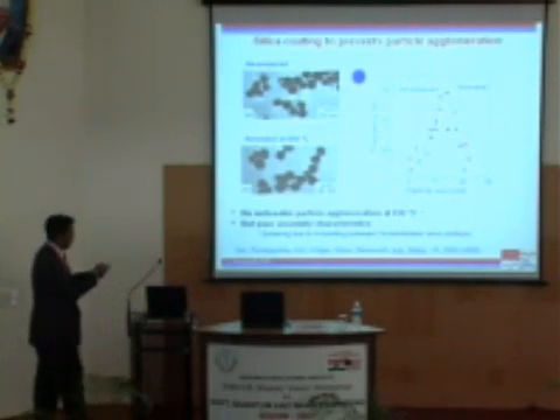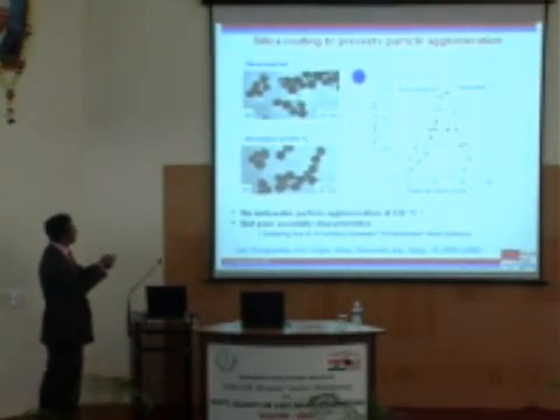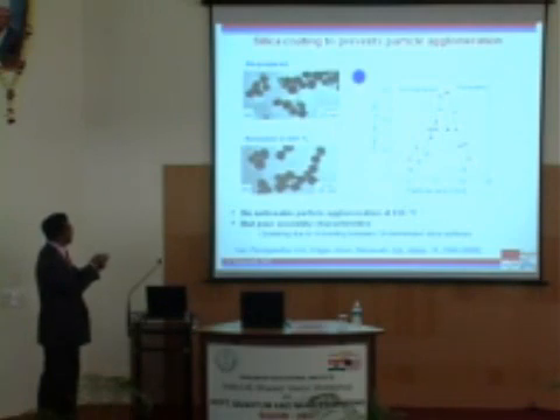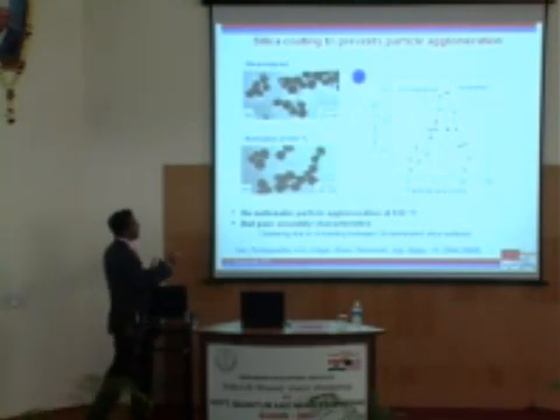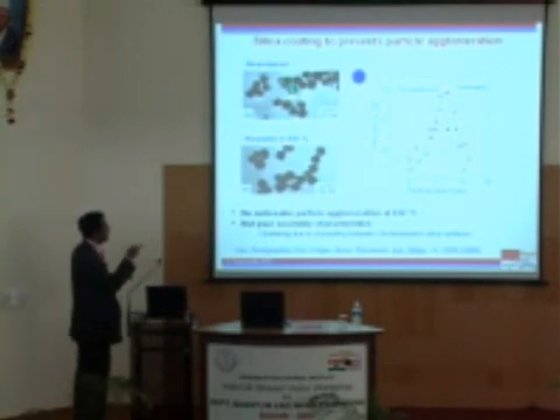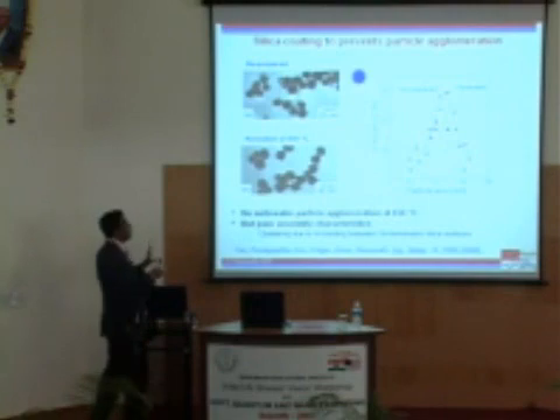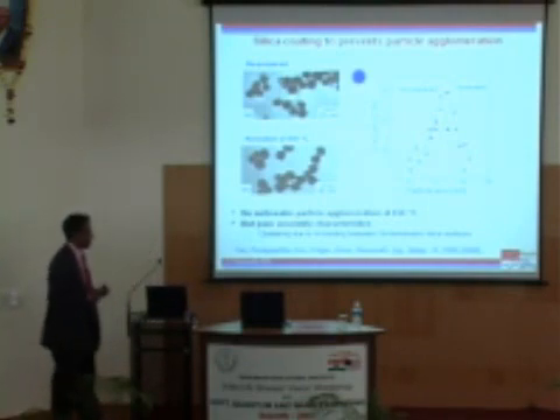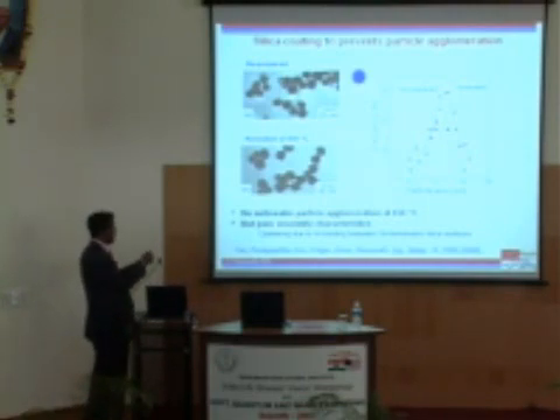And once you have this thin silica shell, in the as prepared form, it looks like this. And once you anneal it, you see that they don't coalesce. They're not agglomerated. I mean, they're kind of sticking to each other, and I'll tell you why in a moment. But the point is, there's no change in the particle size. That's quite important. So we have solved the problem of change in the shape. That's good. But the assembly still looks very bad.